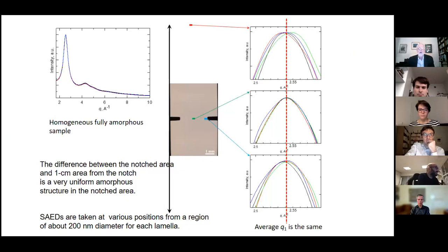And we've looked at it in terms of the diffraction as well, and this possibly ultra-stable like metallic glass has remarkable consistency of these S of Q peaks, where otherwise elsewhere out here in the untreated material, they're locally quite variable. That variability has gone away in this central region.